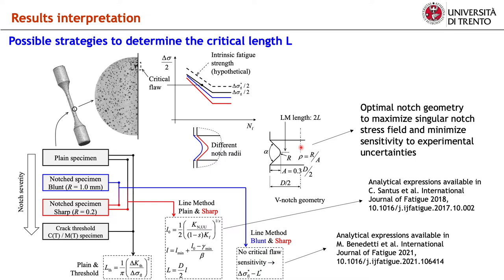To overcome the above discussed shortcoming, we explore in this work a third approach, termed "blunt and sharp," wherein the distance L is inferred from two notch geometries with different notch severity. The fatigue characteristics determined this way are representative of the fatigue damage mechanism ruling the neighborhood of the notch tip. In this way, it is possible to deduce, along with the critical distance L star, an intrinsic plane fatigue strength, delta sigma FL star, which ideally represents the fatigue strength measured using miniaturized plane samples extracted from the notch tip.